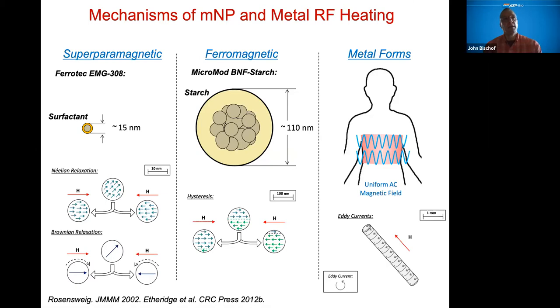And it really works because the radio frequency fields that excite these nanoparticles and metal forms are able to traverse through the biological system relatively unattenuated. It's not that there's absolutely no interaction, but it's a very small interaction that we can compensate for. And so we're working with both superparamagnetic and ferromagnetic nanoparticles, as well as metal forms which have eddy current heating.